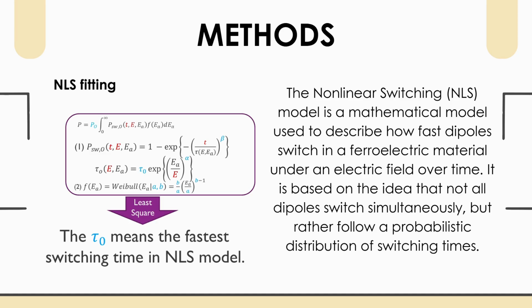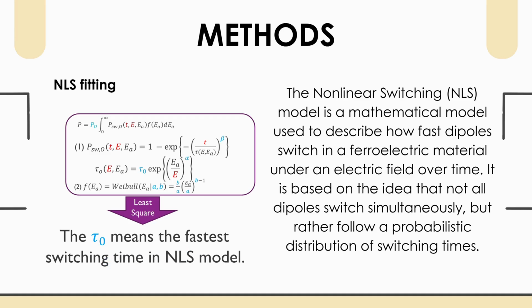And next, to understand how fast the sample switches, I use a method called the nonlinear switching model. It fits a curve to our data of polarization versus time and tells us how fast the material starts switching. The key value we get is tau zero, the fastest switching time. A smaller tau zero means the sample can switch quicker, which is important for fast memory.